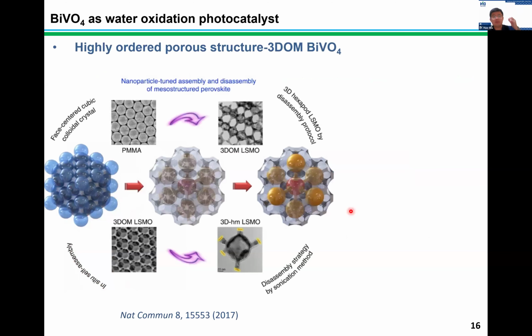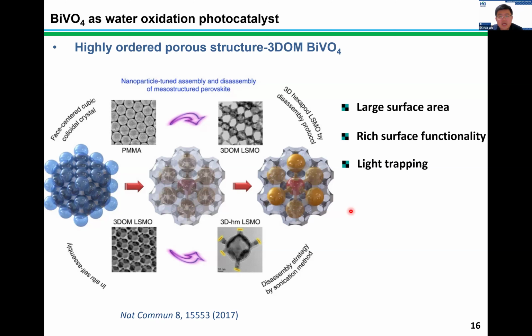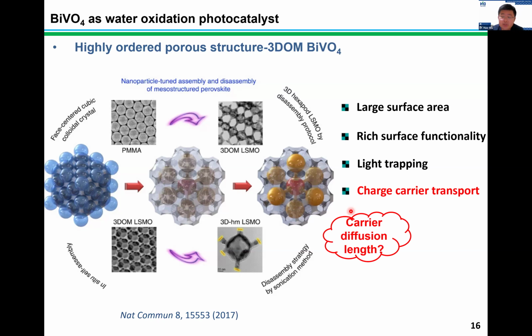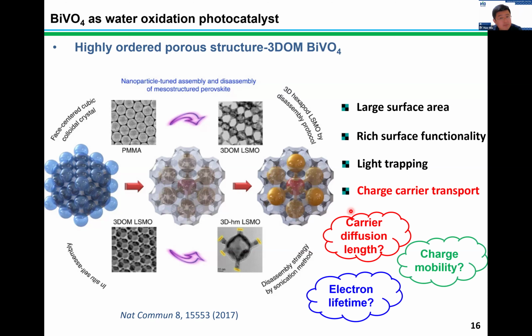So in 2017, my PhD group, run by my professor Mao, published a paper in Nature Communications, which investigated the nanoporous structure of perovskite in photocatalysis. Such a unique structure attracted me a lot because it has many obvious advantages, such as large surface area, rich surface functionality, a strong light trapping effect, and until recently, more and more groups noticed it has different charge carrier transport behaviors. However, how about the intrinsic carrier properties between the three-dimensional bismuth vanadate and the bulk counterpart? The understanding is very limited. For example, how about their differences in carrier diffusion length, charge mobility, and electron lifetime?